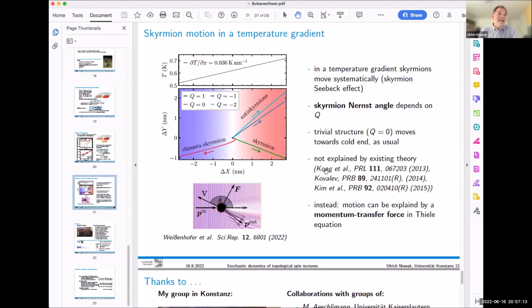At least we can say that we have the theory, the analytical one, resting on the Thiele equation plus simulation. So at least that agrees. But regarding experiments, no, there's not much. The point is, in experiments, much of the dynamics is defect dominated. So mostly, for example, diffusive motion to investigate is very difficult. There's not much work done. They do this in Mainz, and some other groups are also trying, but you need a very good film with a low defect density. Otherwise, the skyrmions are normally pinned at defects.